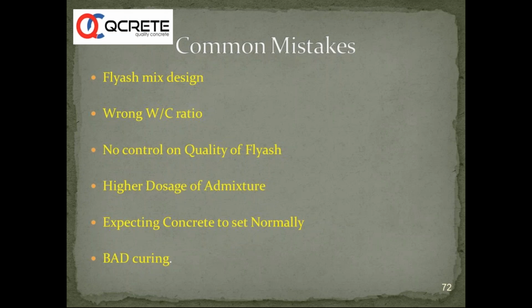We want to tell you very clearly that the advantages of OPC plus fly ash mixes are really remarkable, and we cannot have that much durability by using plain OPC mixes. So plain OPC mixes are nowhere when compared to OPC plus fly ash mixes, especially if you are comparing chloride ion resistance, sulfate ion resistance, and things like that. So the overall durability is pushed to the next level when you are using OPC plus fly ash concrete, and hence to get that benefit, we need to invest in curing. We need to extend the amount and time of curing, and take care of the concrete in the initial stages.